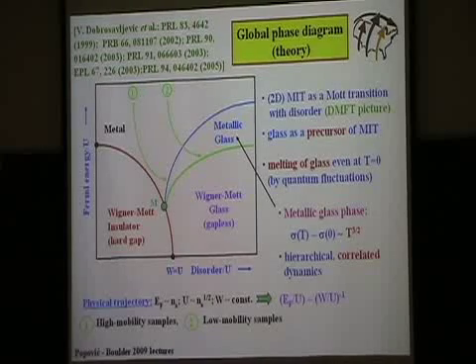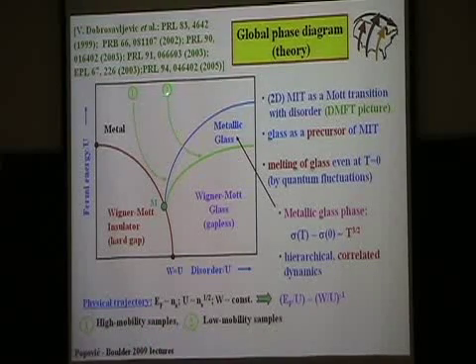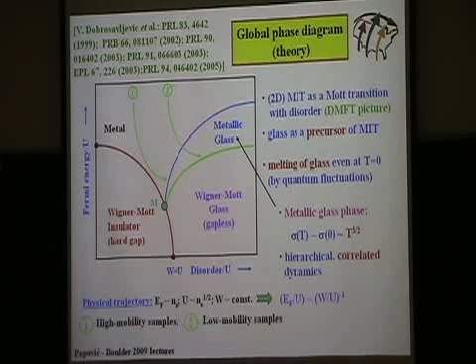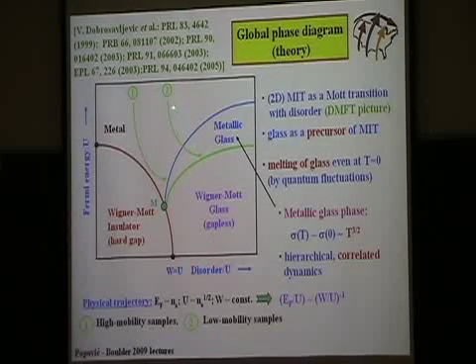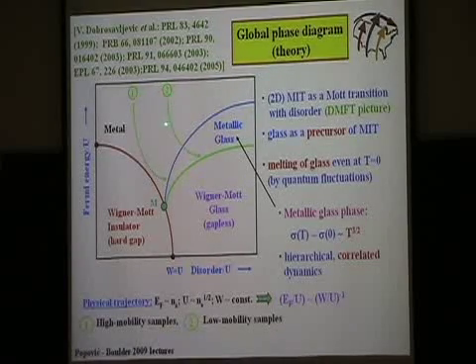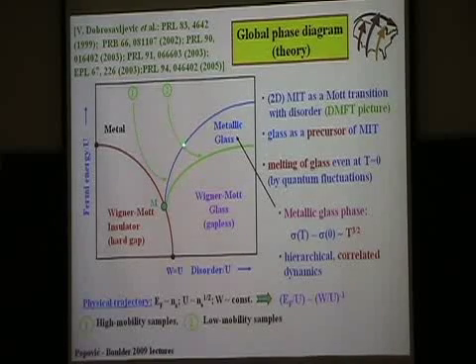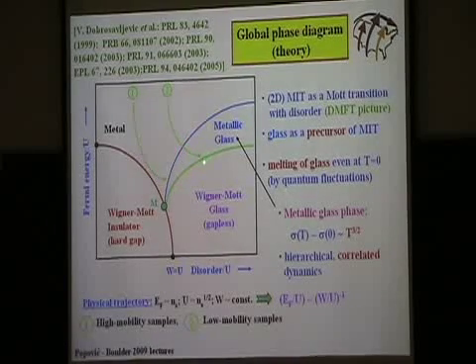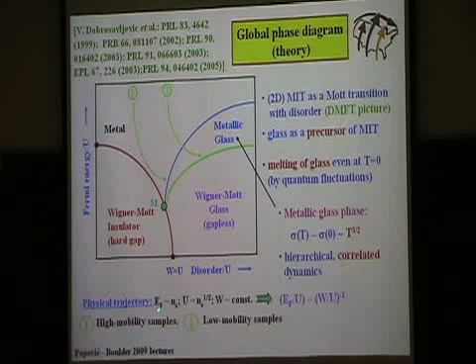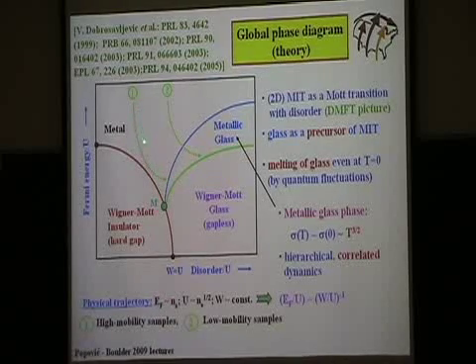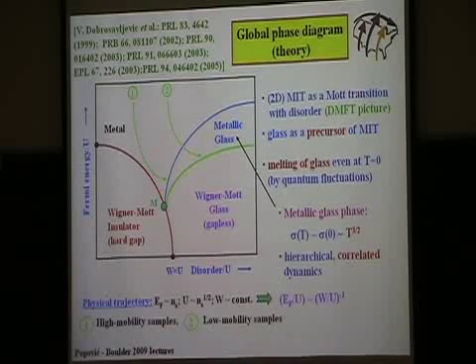In the experiment, we changed the carrier density. So the experimental trajectory will be like this. Okay, so when we have a lot of disorder, we will be going this way by changing our density. So we go from high density, reduce it, and we go through this metallic glassy phase into the insulator. For low disorder, we will be here on the phase diagram, and this metallic glassy phase will be very small or even non-existent.